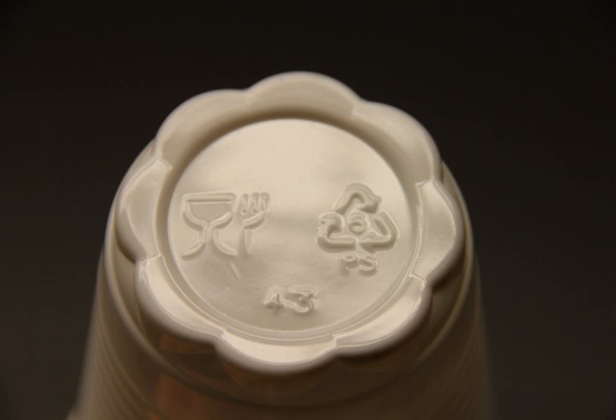Many customizations, additives and thin additional external layers on one or both sides are often added to help with various properties. Thermal conductivity is measured according to EN 12667. Typical values range from 0.032 to 0.038 W/mK, depending on the density of the EPS board. The value of 0.038 W/mK was obtained at 15 kg per cubic meter, while the value of 0.032 W/mK was obtained at 40 kg per cubic meter, according to the data sheet of K710 from Styrochem Finland.